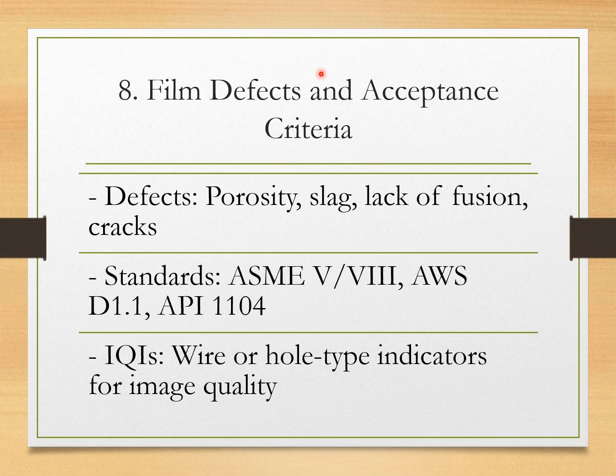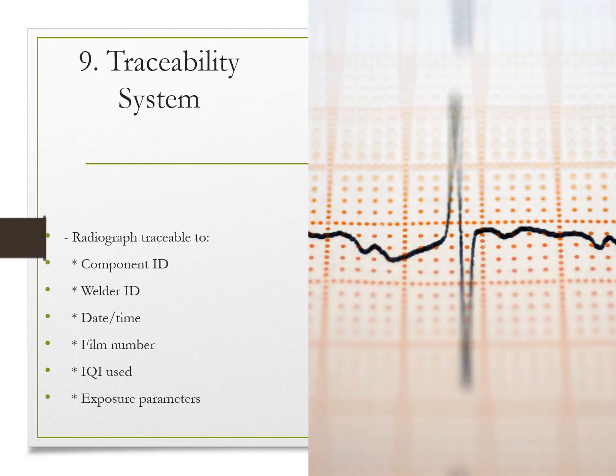Film defects and acceptance criteria. Defects: porosity, slag, lack of fusion, crack. Standards: ASME V, ASME VIII, AWS D1.1, API 1104. IQI is a wire or hole type indicator for image quality. Traceability system: radiography traceability links to component ID, welder ID, date and time, film number, IQI used, and exposure parameters.